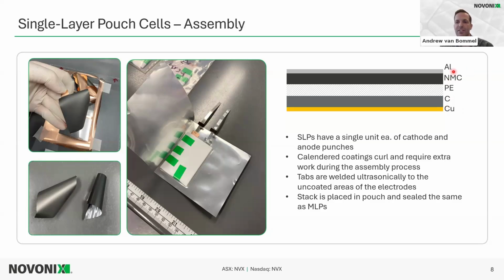When we make these single layered pouches, these use calendered coating. So that's when they're pressed under pressure to ensure that there's good compaction density of the electrode. But the issue with this is that there's a lot of curling when you perform that calendering step. So there needs to be extra work in this assembly process. So we have a few jigs and a few ways to assemble the single layer pouch. And here's the final single layer pouch.